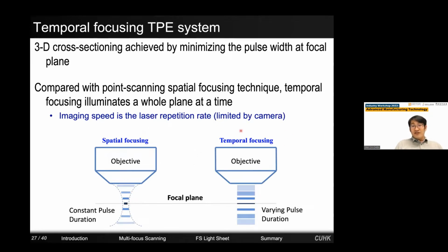In a temporal focusing system, we do not focus the laser beam. The laser beam diameter is adjusted to be equivalent to the processing area. As you can see along the light path, the pulse width is varying instead, and only at the focal plane, the pulse width is narrow and can have multi-photon effect. This idea was actually not invented by our group, but by some of the microscopists in 2005.